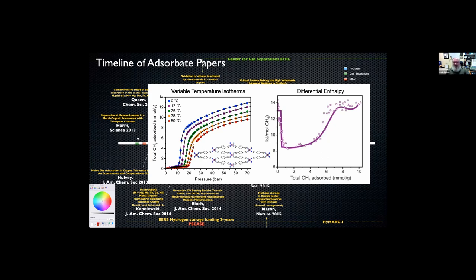And we were looking at the structure of this material. The useful thing here is that there's an automatic enthalpic balance as you get a strong interaction initially with the framework. Because it takes energy to open, there's a drop in the differential enthalpy as you're expanding this framework. And so it's beneficial in terms of heat management for these systems.